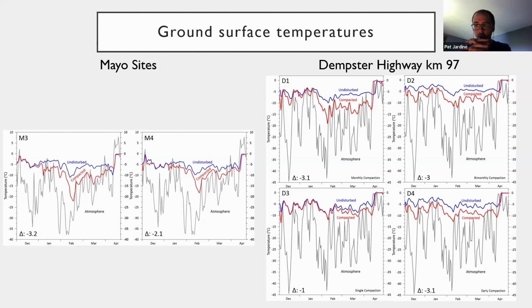So from these loggers, we can see a surprising trend. Even though compaction created a much larger change in snow physical properties at the Mayo sites, the temperature changes at the ground surface were pretty similar. It's difficult to compare between sites, especially considering the Dempster plots mostly had different compaction schedules, but it's fair to say the compaction was effective at reducing mean daily ground surface temperatures by about 2 to 3 degrees Celsius on average at both locations, even though most of the snow at the Dempster Highway was resistant to its effects.